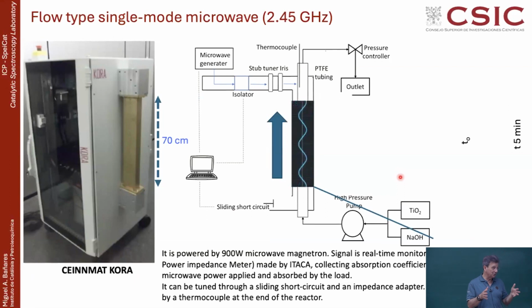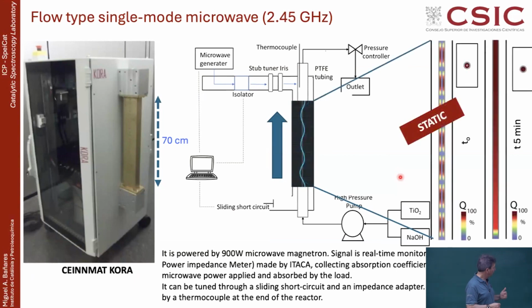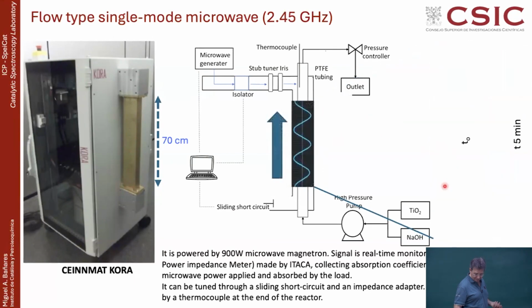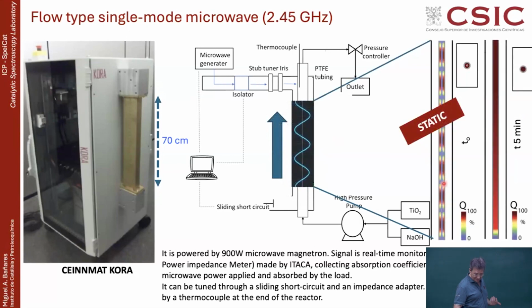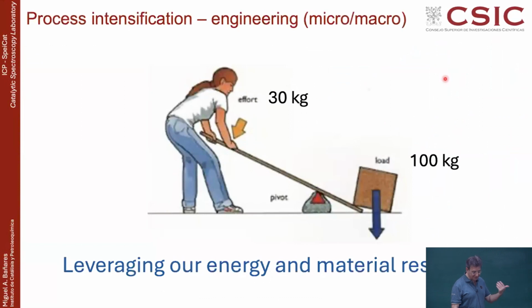It's very efficient. Now, the microwave in the kitchen is a multimode. A multimode is not an optimized system, it's not very energy efficient, but you can see that they heat very quickly, very fast. When you go to monomode, what you have is a standing wave inside the cavity, and basically the catalyst is at the maximum intensity of the standing wave. So the heating is with the maximum possible efficiency that you can get with microwaves. And that is important because the field has local maxima. So when you are making a synthesis, and you are flowing, what happens is that you have a hot spot, cold spot, hot spot, and this is 70 centimeters. But because this is a flow system, with liquid flowing through it, after a while everything gets homogeneous, so you get a very homogeneous heating within the system, and then you can control very nicely what is happening. And the energy efficiency is much better.